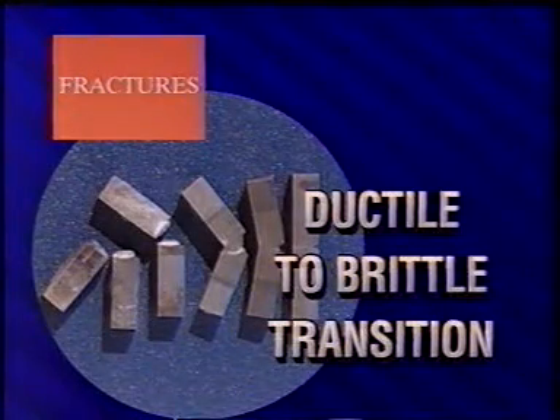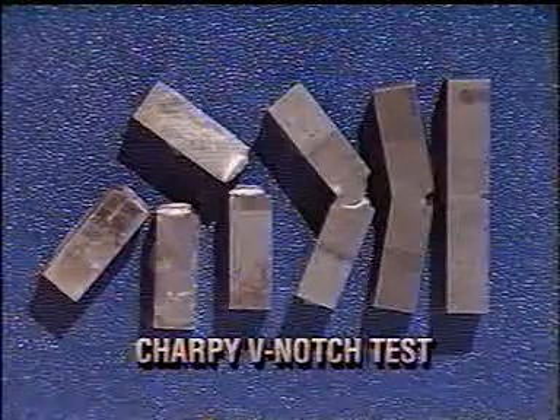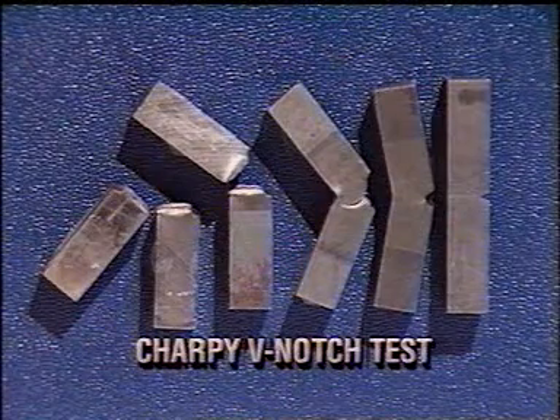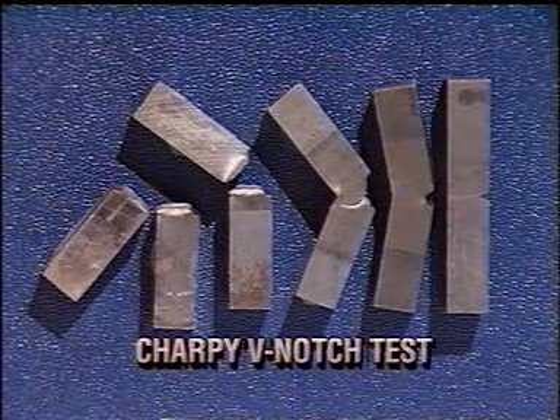Ductile to brittle transition. Some metals undergo a ductile to brittle transition in their fracture behavior at low temperatures. Fractures arising from ductile to brittle transition have an especially insidious character. They may occur without warning, and they may occur under static loading at stresses well below the nominal yield strength. This brittle fracture is induced in certain relatively ductile metal by low temperatures or impact and is usually associated with notches. The ductile to brittle transition can be demonstrated quite readily by the Charpy V-notch impact test.